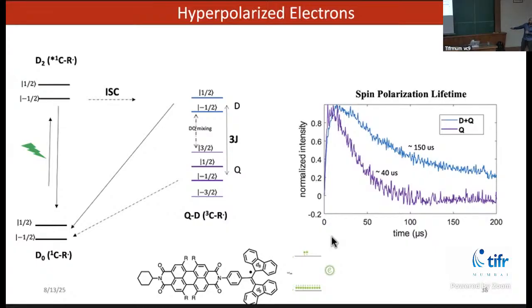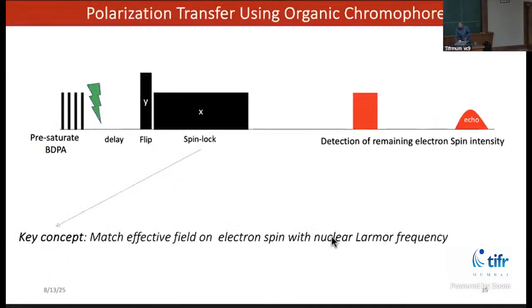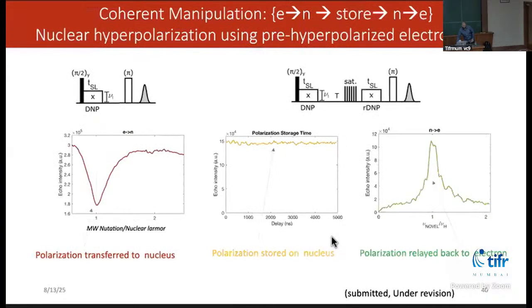This was done at 85 Kelvin. But there are molecules which are not very efficient, but they can hyperpolarize even at room temperature. We used EPR to do this experiment, and for the EPR, we did not have the time for an NMR measurement. So what we have shown, just as a proof of concept, is that the hyperpolarized electron spin can do the DNP transfer to the nuclear spin.